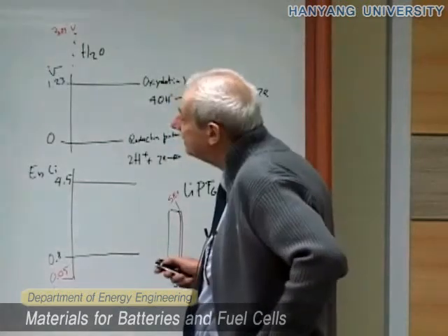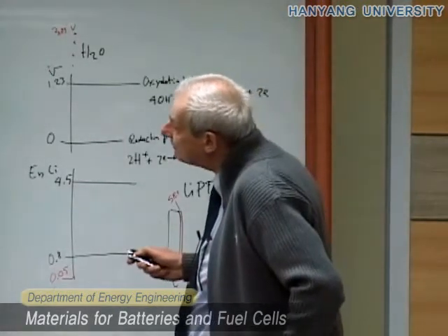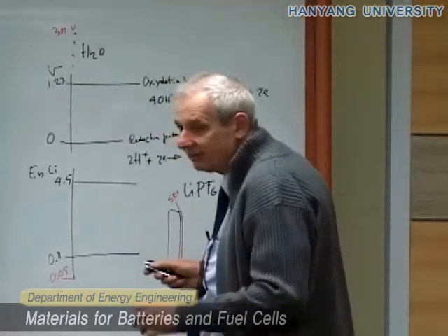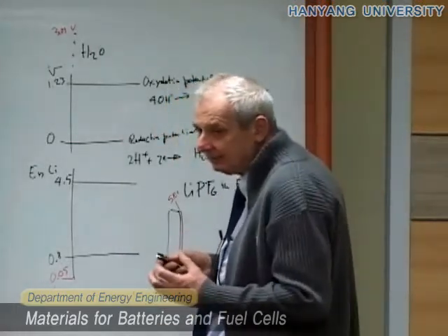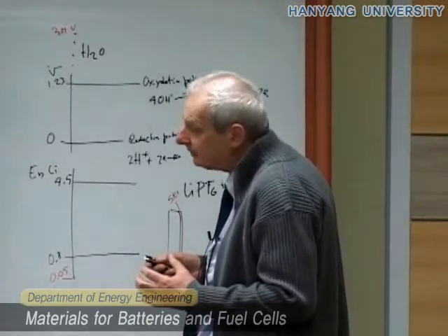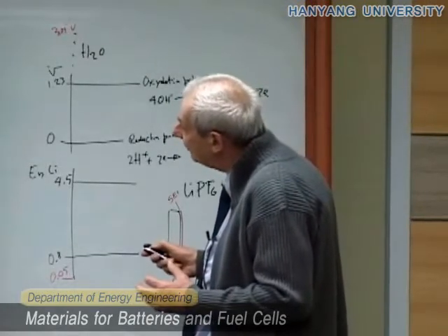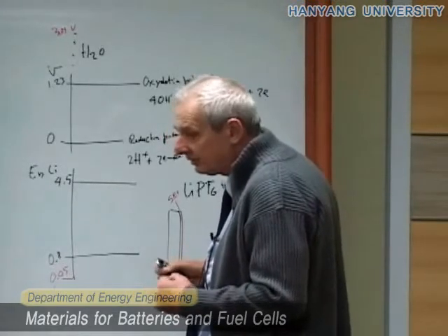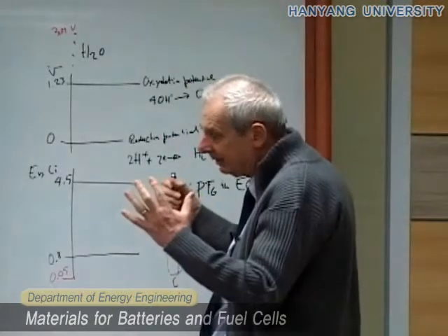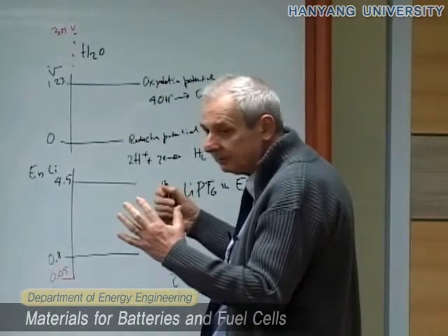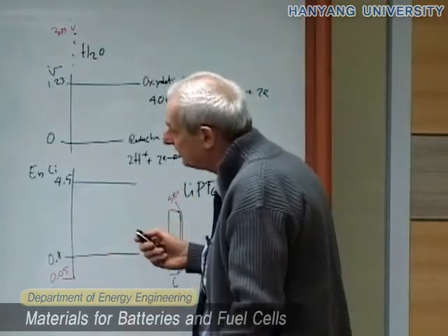Because we will go back into this area here, the decomposition, with the formation of gas inside the battery. So we may have some pressure built up in the battery, and also some problems because the pressure may open the battery. As soon as the battery opens, it gets in contact with air. We have some fire or explosions.